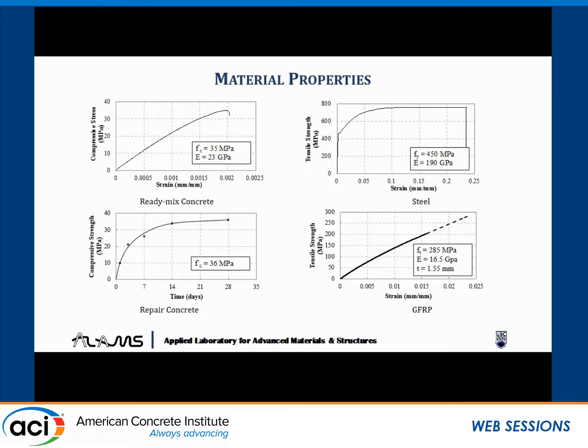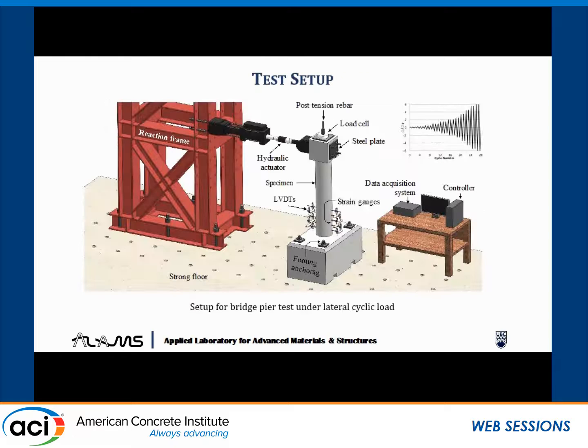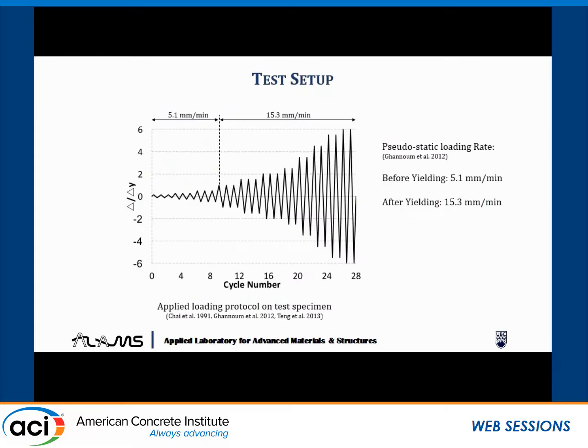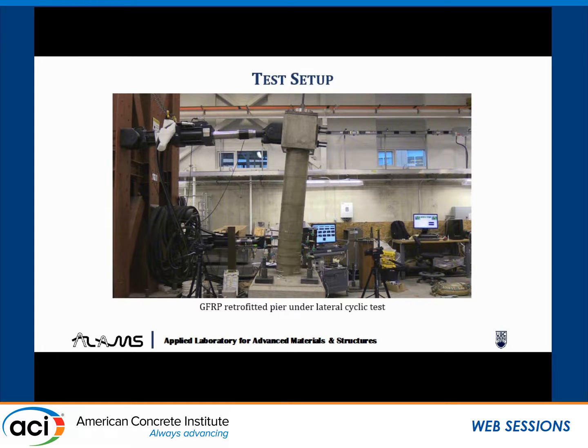We also tested the coupon for tensile strength, and then our setup was ready for doing the testing. So this was the test setup where we followed the standard loading protocol. The initial stage before yielding was 5.1 millimeter per minute, and next we increased it 3 times to 15.3. So this is the test setup showing.